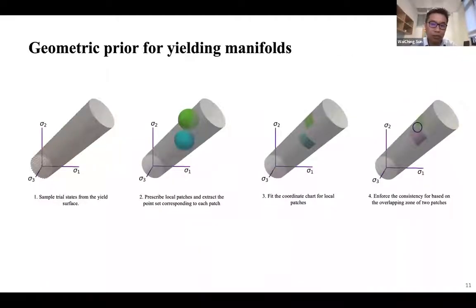Okay, so from a procedure perspective, I would explain what they did here. Imagine that the true answer is just a von Mises yield surface. That would make this approach completely unnecessary, but for the argument's sake, let's do that. Then if we measure the yielding of a von Mises material, we will get those point clouds that are on the cylindrical object. Okay, we can partition those point clouds using Poisson disk sampling. And then we can learn the local coordinate chart mapping one by one to form a local patch. And then the final machine learning procedure is to make sure that in the overlap regions, the two patches are consistent with each other.